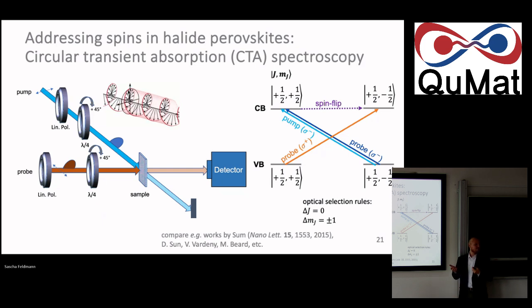Now, we haven't populated that state to begin with, so at time 0, you also wouldn't expect to see anything there. Only if time passes by and there would be some sort of spin flip occurring, would you expect to eventually have populated that state and therefore see something there. And eventually, of course, spins would randomize, and all of that would happen within your excited state lifetime. And this is not something we've invented. This has been shown by Valy Vardeny, Matt Beard, and some others, and is really lent from the older spintronics folks. But it works very well for perovskites.